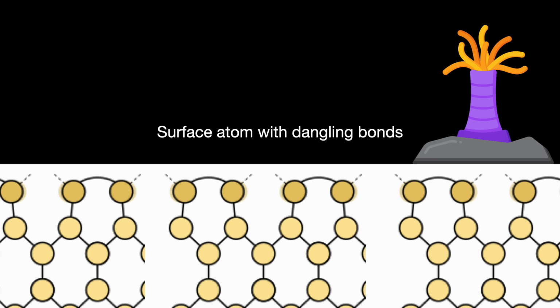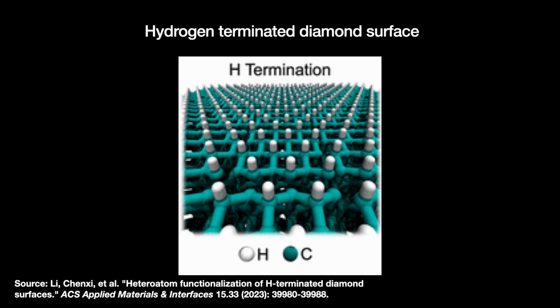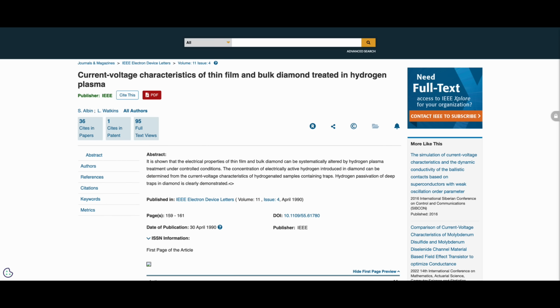The result of this termination is a very thin layer of diamond that electron holes can travel through, giving us p-type conductive diamond while sidestepping the whole boron doping problem. It triggered a lot of research in the 1980s to confirm. Upon confirmation that it was indeed the hydrogen termination doing this, we were able to finally make switching devices. The first serious field effect transistor with diamond emerged in 1994.